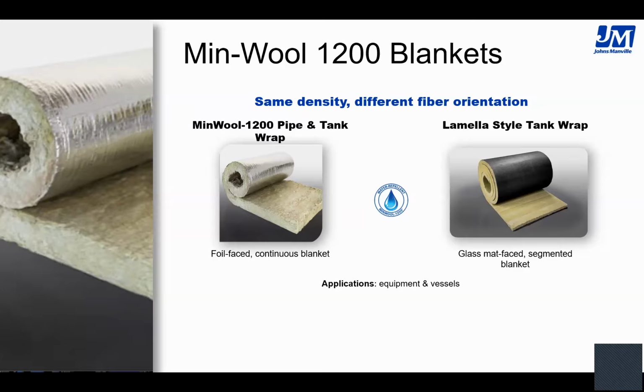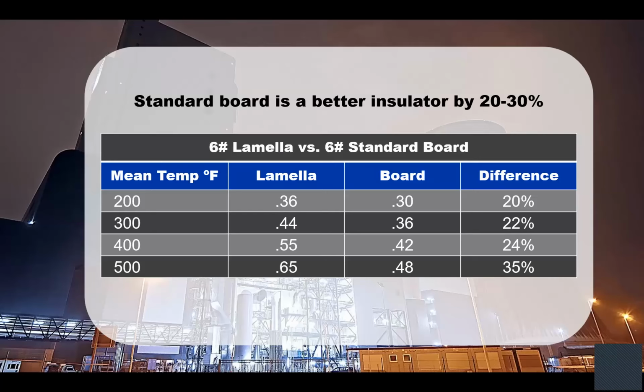The interesting thing, and I just want to point this out, is both of these products might be made out of 6-pound density material, but simply due to the fiber orientation, the thermal conductivity, the K factor, the insulation value, however you want to look at it, is different. It's primarily due to the orientation of the fibers. Fibers that are parallel to the surface insulate better. It provides a more difficult path for the heat to move through the material versus perpendicularly set fibers.